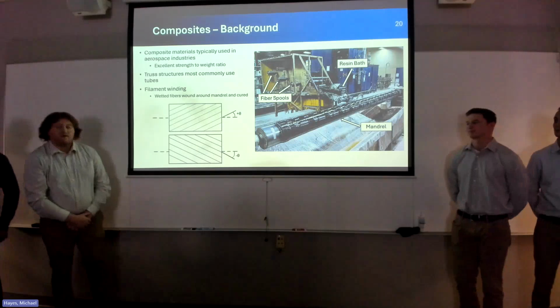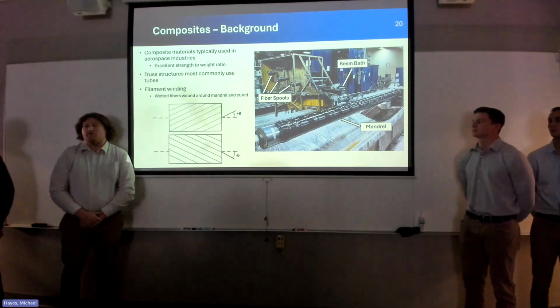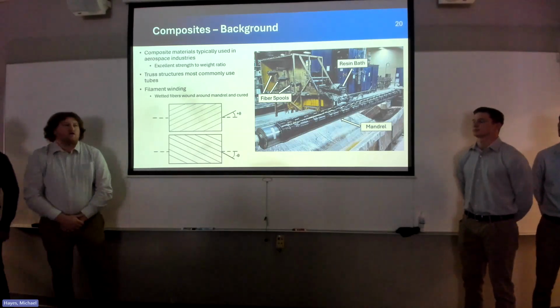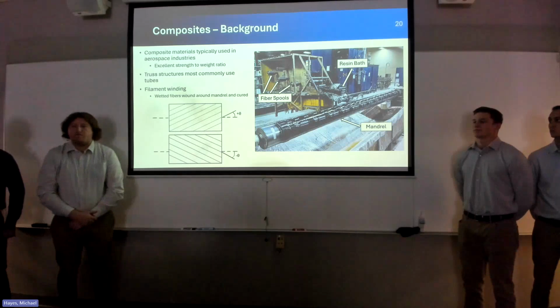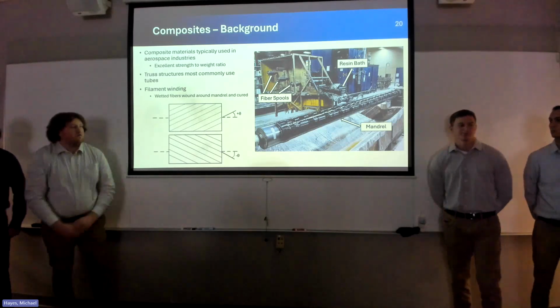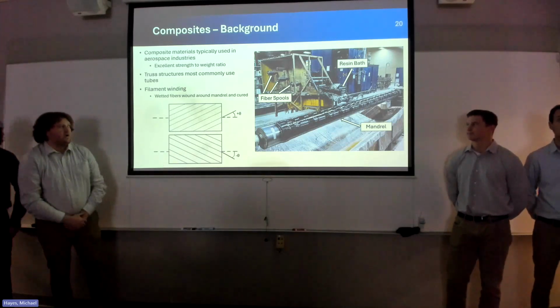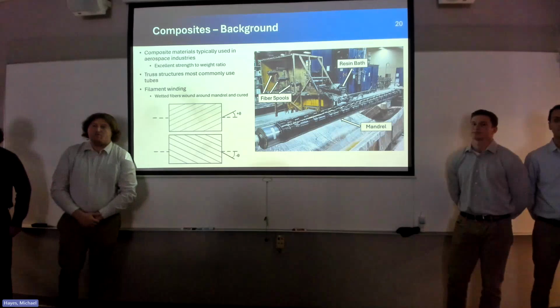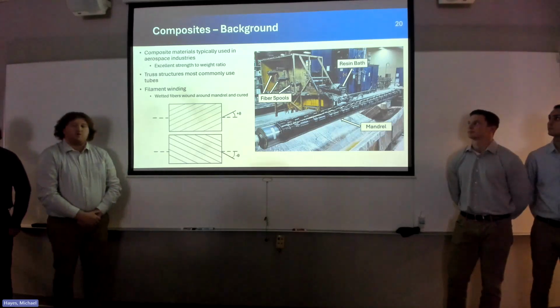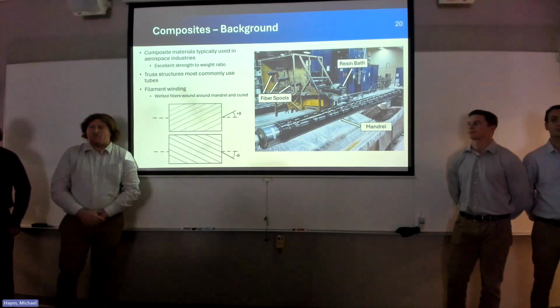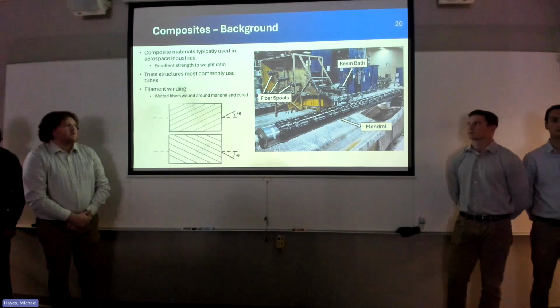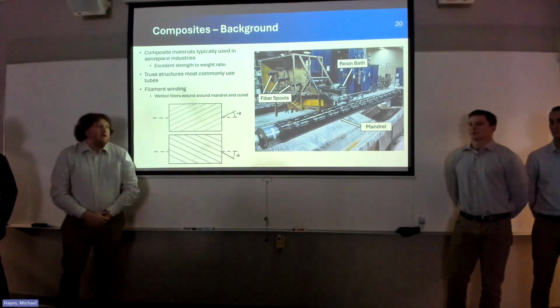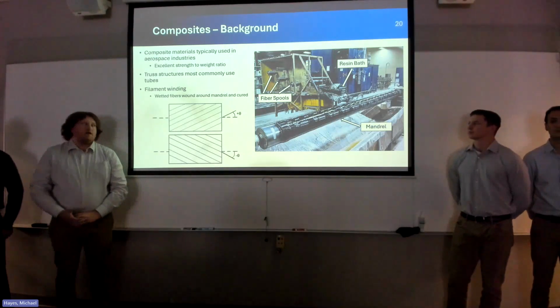Truss structures typically use tubes for a majority of their members, and the best manufacturing method for composite tubes is a filament winding process. A generic filament winding process is shown in the picture on the right. In the top left, fibers are being pulled off of spools and fed through a resin bath, essentially wetting the fibers with resin. Those wet fibers are then wrapped around a mandrel,